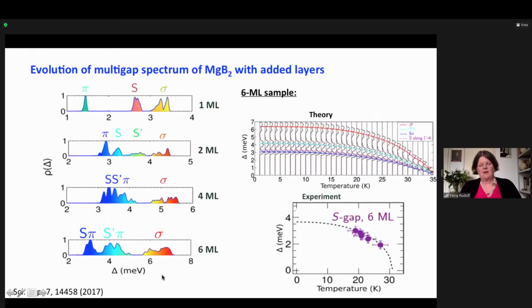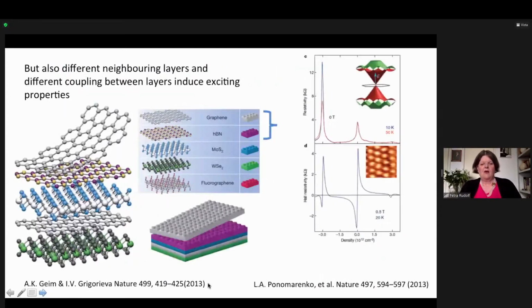And that is actually something which is also very exciting in perspective, because it tells you that when you make very thin layers, really surprising things happen. And that is now taken further by looking at how one can combine these layers and have coupling between neighboring layers to induce exciting properties. That was first proposed by André Geim and his wife in 2013. So Irina Grigorieva has worked a lot on the optical properties since then. Other people have looked at other properties of these layers.